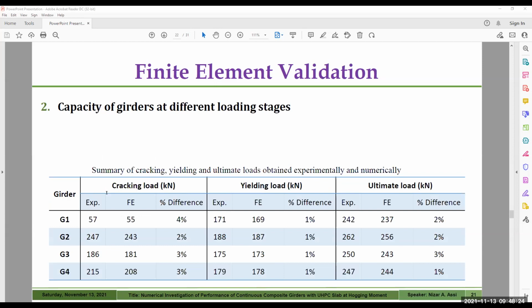In addition, validation was conducted using cracking, yielding, and ultimate loads. This table summarizes the values of the cracking, yielding, and ultimate loads obtained experimentally and using finite element software. The percentage difference between the experiment and the finite element is less than 5%. Here we conclude that the developed model is very accurate in terms of these loads.